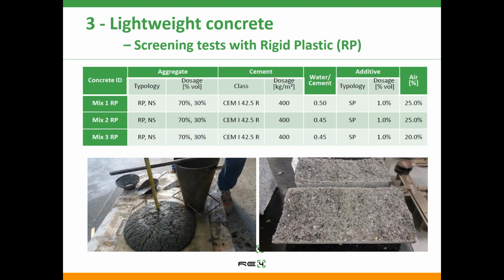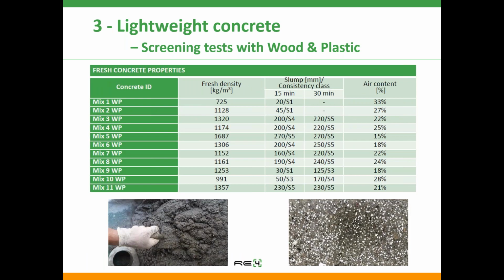So moving on to the lightweight concretes, again, initial tests with rigid plastic. We have the aggregate, the cement, the water, and the additive superplasticizer was used. And as you can see, there is a high percentage of air voids in them. They all had to be flowing concretes. Again, the same thing, initial tests with a mixture of wood and plastic. And you can see the wood and plastic in the cut section.